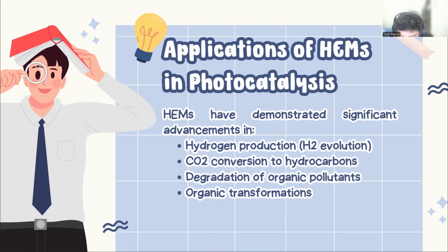The prepared HENNF comprising Ti, Hf, V, Ta, and Mo uniformly dispersed metal elements exhibit a face center cubic structure with a broad absorption wavelength range, and high selectivity for photocatalytic CO2 conversion to CH4. Photocatalytic CO2 reduction exhibit high selectivity of 96.4% and no performance degradation was observed over 5 test cycles.